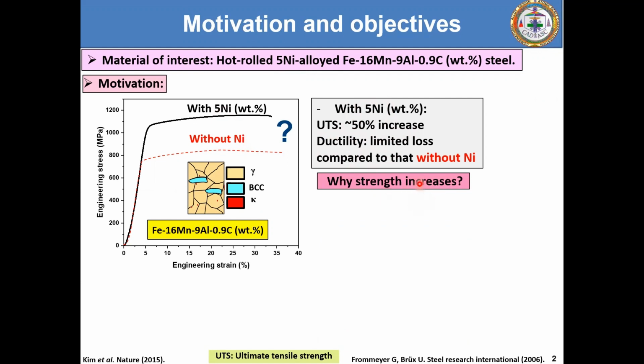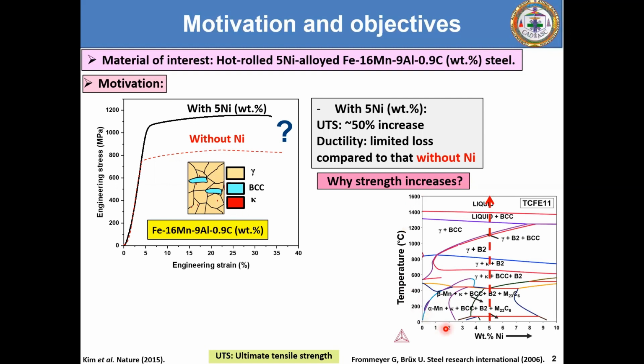To understand that, we have initially embarked upon performing the thermodynamic calculations by varying the weight percent of nickel in this particular system. And what we can clearly observe is that the addition of 5-8% nickel, or rather in general, the addition of nickel basically leads to the stabilization of the B2 NiAl phase in this system as predicted thermodynamically from here. And this is very much in contrast with the 0 weight percent nickel, where the typical microstructure would not show a B2 phase at all. And the same can also be inferred from the thermodynamic predictions here.